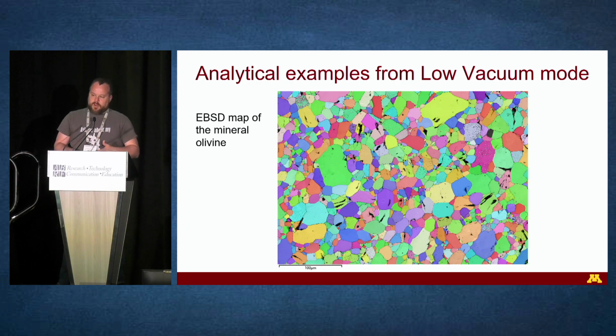You can't get quite as low a resolution as you could with regular SEM imaging, because this signal has slightly worse resolution due to the high tilt. The beam spreads out a bit in the y-axis, and also because it's coming from a deeper part of the activation volume. So with more material in there, it's just a bit worse resolution. But you can generally get between 50 and 100 nanometer resolution at best.